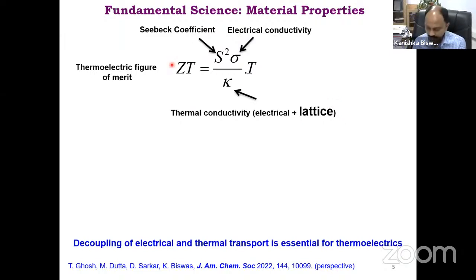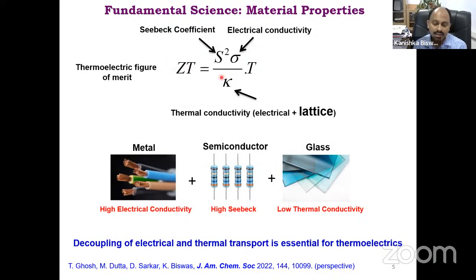I am a solid state chemist, so I think about this problem in a slightly different way. We have to have a high electrical conductivity, so we need a property of a metal. We need a high Seebeck coefficient, which is a property of a semiconductor, and we have to have a low thermal conductivity, as it is in the denominator, so we have to have a property of glass. Thermoelectric materials should have metal, semiconductor, and glass properties together, which is extremely challenging, and where chemists have a very big role to play, because they can make new materials by utilizing the concepts of chemistry and chemical bonding, where we can implement metal-like, glass-like, or semiconductor-like properties in a single material, which is the grand challenge in this field. So we have to have a metal, semiconductor, and glass in the same material to have a good thermoelectric.